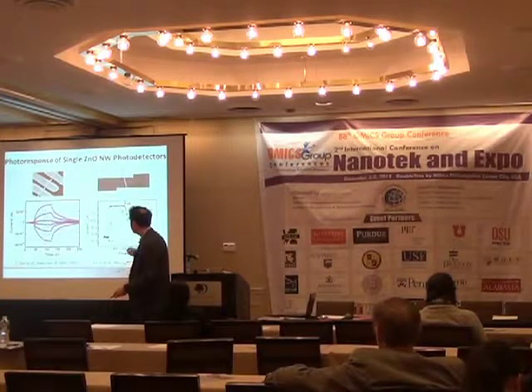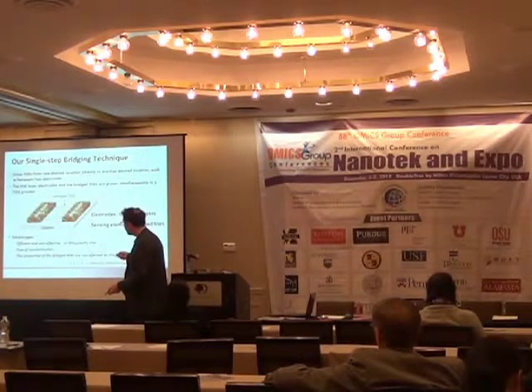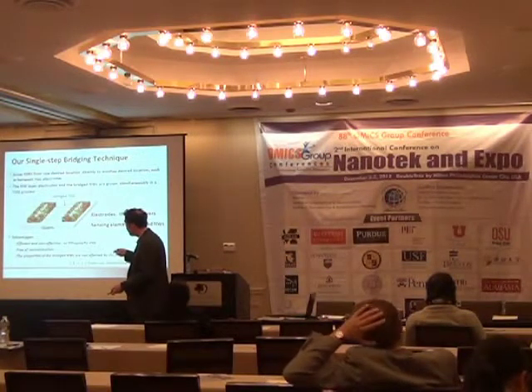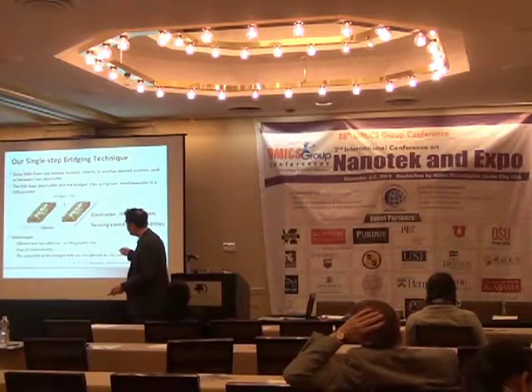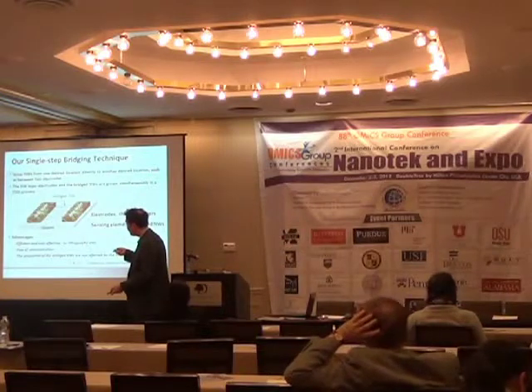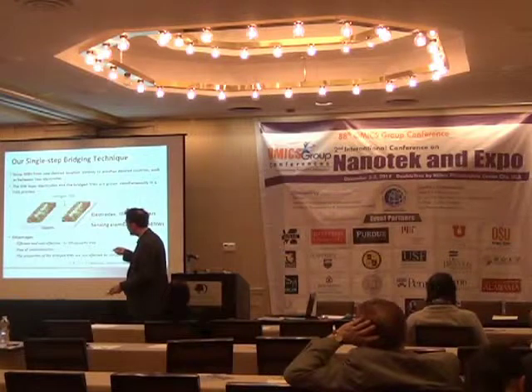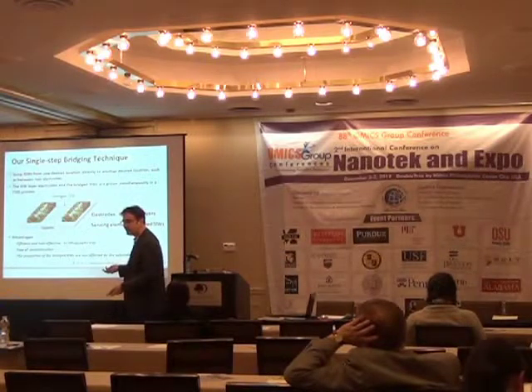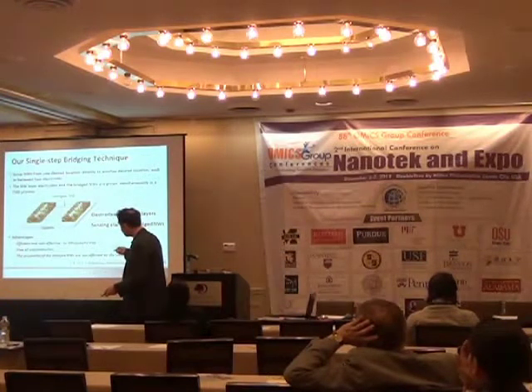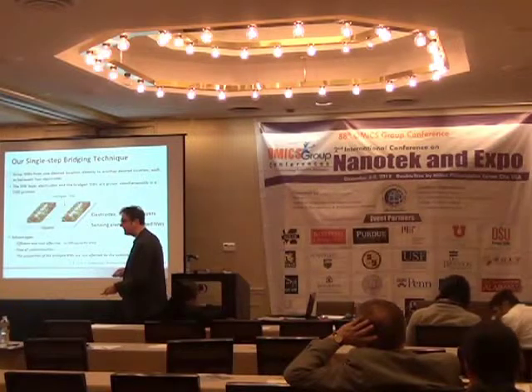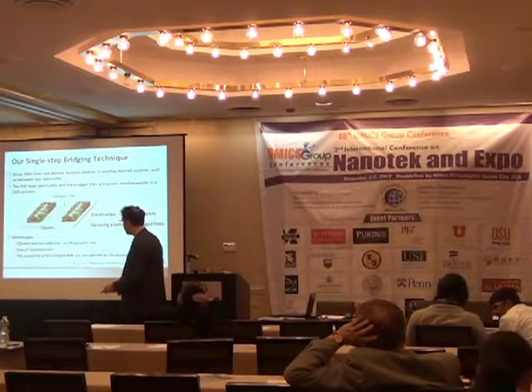So there are a lot of small parts to this type of design. What we propose is to grow two thick layers of nanowires that are full of defects, so they have a very low resistance, and to bridge them with nanowires. That's the simple technique that we have. The part that is sensitive to UV is the nanowire here in the middle, and these thick layers are used to make the contact and get the signal.